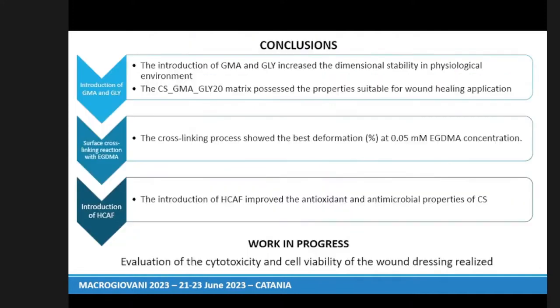To sum up, I want to say that the introduction of GMA and GLY increased the dimensional stability in a physiological environment, and the concentration of 20% allows to obtain a matrix that can be used in wound healing application. The cross-linking process allows to obtain the best deformation percentage only in the lowest concentration of EGDMA, and in the case of HCAF, we obtain an improvement of antimicrobial and antioxidant properties with respect to chitosan used as standard.